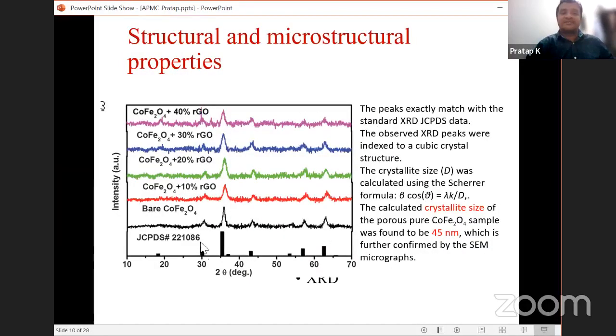These are the structural characterizations. The black one is bare cobalt ferrite, red is cobalt ferrite with 10% RGO, green is with 20% RGO, blue or purple is with 30% RGO, and this color is with 40% RGO. Here, the peaks have exactly matched the JCPDS data. The observed crystal structure is cubic, and the crystallite size is calculated using Scherrer's formula, D = Kλ/(β cos θ). The calculated crystal size of this porous sample is found to be 45 nanometers. When we check the SEM, it is almost the same, so SEM has confirmed the calculated crystallite size.